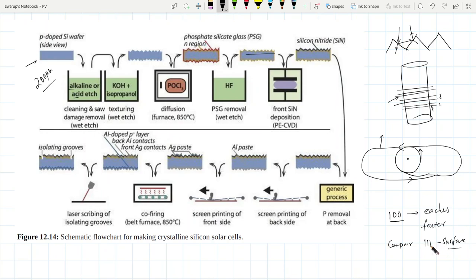The 111 surface, for any crystallographic structure, is generally a diagonal surface in the lattice structure. So the facets it will create after removing will create a pyramid-like structure in three-dimensional space. I'm not able to draw it, but you can imagine a pyramid structure. The other surfaces, like 110, get etched off. Earlier it was a plane surface and this material got etched off because it falls in the 110 plane, but finally the 111 surface will be left. So we get this kind of surface structuring after this wet etch. We have got the pyramid structure here.